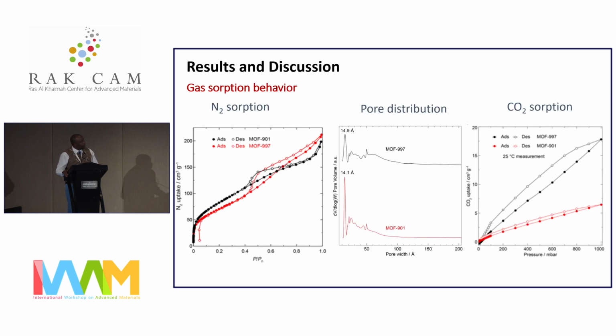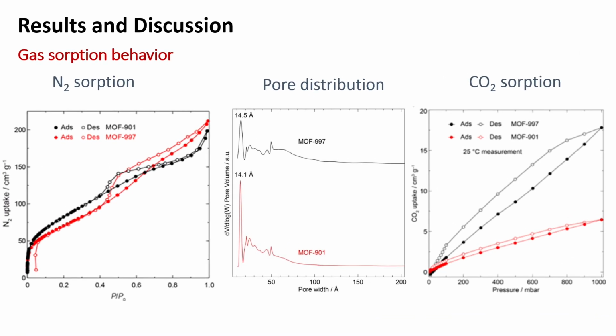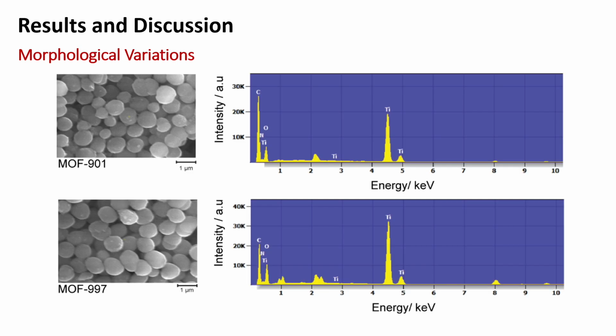Then we followed through with the sorption behavior. We saw that the two materials had comparable behavior. Both of them had type 2 isotherm behavior. The pore distributions were more or less the same, except that MOF 997 showed slightly higher pore diameter, and MOF 997 actually was amazing in CO2 sorption behavior, with sorption 3 times more than that of the pristine MOF 901.